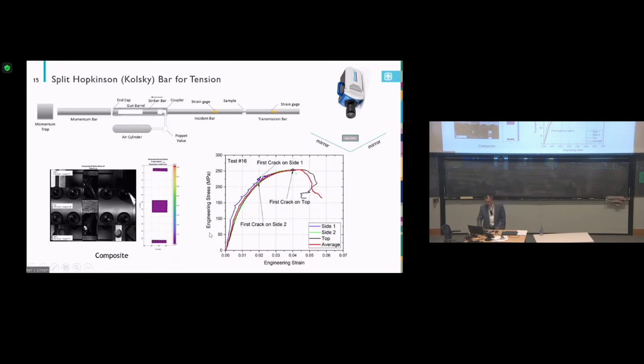Like this here, you can see the top surface. You can see there's a side surface, another side surface. Then we have the speckle pattern over there. We use DIC to understand the failure strain and where or when the first crack starts. When we pull the sample, the high-speed camera is pretty slow. You can see there's a shear fracture on the top. But after we ran the DIC analysis, we found the crack on the top is not the first crack. Actually, the first crack is on the side. So that's the data point from here. Basically, if you do the DIC on this surface and on this surface, you will see the first crack on both sides, but not on the top surface. That helps us understand the maximum strength of this material, and the behavior of this material. So that's the composite.